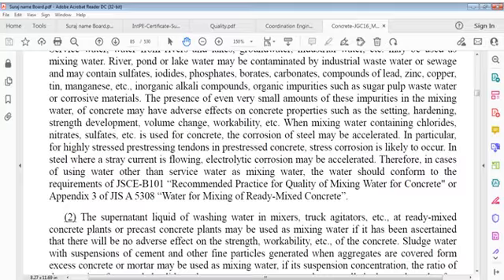When mixing water containing chlorides, nitrates, sulfates, etc. is used for concrete, corrosion of steel may be accelerated. In particular, in pre-stressed concrete, for highly stressed pre-stressing tendons, stress corrosion is likely to occur. In steel where a stray current flows, electrolytic corrosion may be accelerated. Therefore, water other than surface water used as mixing water should conform to the requirements in the recommended practices for quality of mixing water for concrete and Appendix 3, water for mixing and ready mixed concrete.